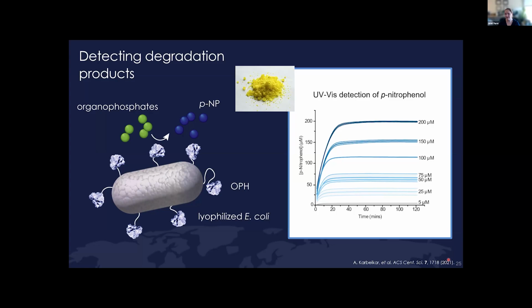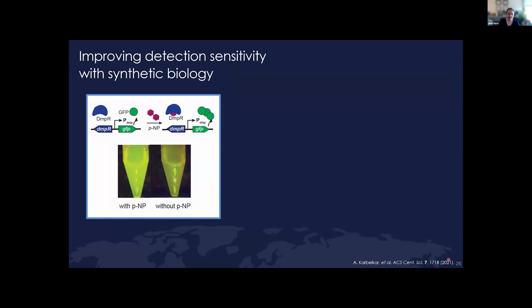So our second question: now that we have these materials that can degrade this effectively, how do we actually sensitively and reproducibly detect the degradation products? And so we turned to biology. We were very lucky and we found a transcriptional regulator, which is just a protein that turns genes on and off, that natively binds to small molecules that look a lot like our p-nitrophenol. So when we put green fluorescent protein under control of this transcriptional regulator, you can see that with the small molecule, as you would expect, we see a lot of green fluorescence.